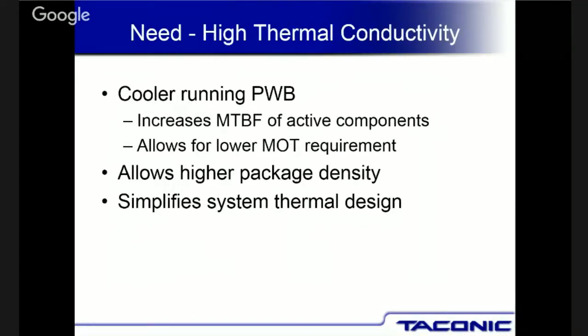Thermal conductivity. What does that give you on a board? Well, the board runs cooler. You get higher packaging density. You can put more components on the board since you can actually run it cooler. The interesting thing about thermal conductivity is that all of these printed circuit board materials, in my opinion, are insulators, because copper has a thermal conductivity of like 390 watts per meter per degree Kelvin. 390, just remember that number.